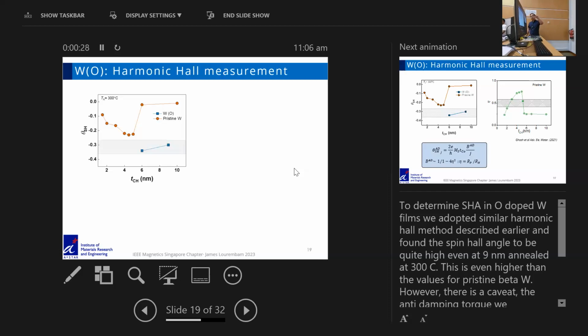But in this case, we find that our beta tungsten has a lower spin Hall angle. The difference is basically because the theoretical calculation is for a perfect beta phase tungsten. But here, as mentioned, after annealing we have the CFB on top, there is the boron diffusion as well as defects because it's a very thin tungsten. So unlike the theoretical calculation with perfect tungsten, the tungsten in our practical case is already compromised. So introducing oxygen is better than the ultra thin tungsten with CFB multilayer, but it is not going to be better than the theoretical calculation of a perfect beta phase tungsten. We are running out of time, so if you have further questions, fine. Thank you.